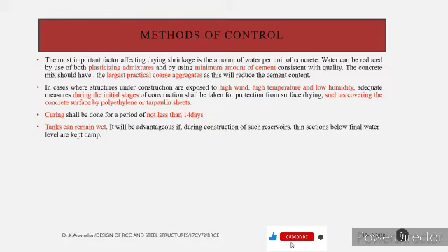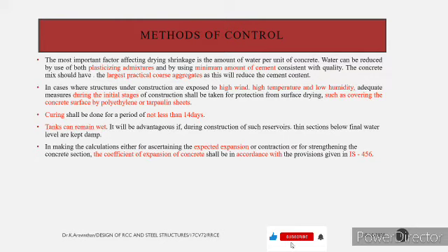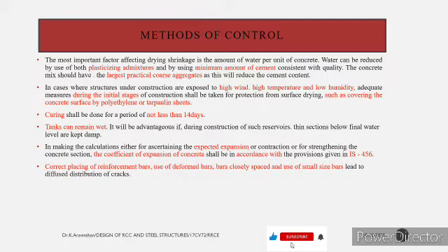Also, you can control the crack by keeping the tank in a wet condition. You have to keep a minimum water depth of D by 4 in the water tank. If the overall depth of the water tank is D, at least D by 4 depth of water should be kept for the initial days in order to reduce the cracking of the structure. There is a coefficient of thermal expansion which is given in IS 456. You can consider that coefficient of expansion and then proceed with the design.